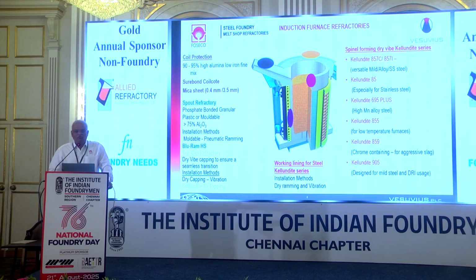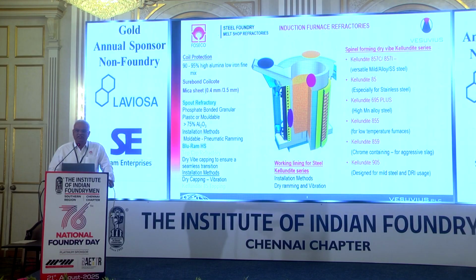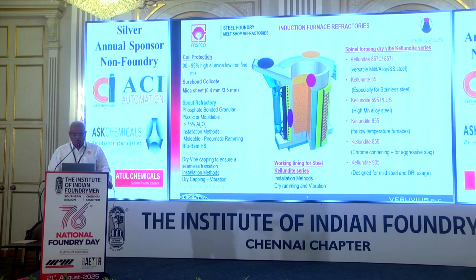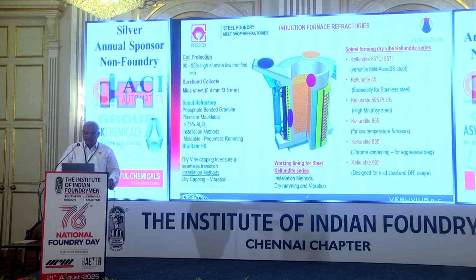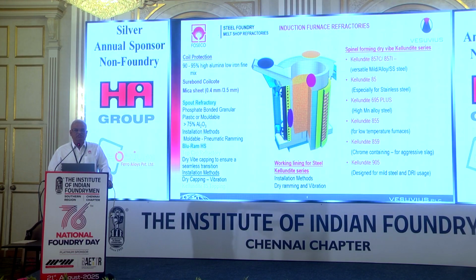The main grade is Kellundite 857, which is versatile and used for all grades, mild steel and stainless steel. But specifically for stainless steel, we have developed Kellundite 85. Kellundite 695 is developed for high manganese alloys. In chrome, the slag is always more aggressive. To overcome this, we have developed Kellundite 859, and Kellundite 905 is designed for mild steel and DRI.